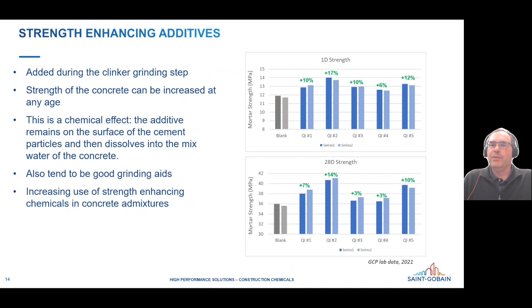And to show an example of this, you can see on this plot we have the results of what we call a lab screening. So a GCP customer will send a sample of their cement to us, and that cement will have been made with a grinding aid rather than a quality improver, so it doesn't have these strength-enhancing chemicals on it yet. And we will make a series of mortars out of it, and when we make those mortars, we will admix in different quality-improving chemicals. So in this case, we've tested five different chemicals. And then, of course, we measure the strength. We can see the one-day strength on the top graph and the 28-day strength on the bottom graph. And we look to see which one of our quality improver formulations is doing the best for this customer's cement.